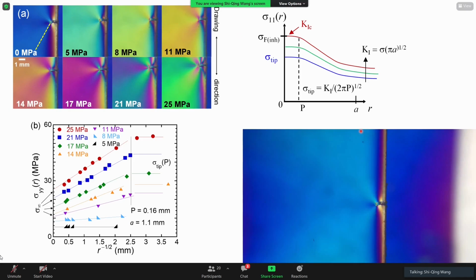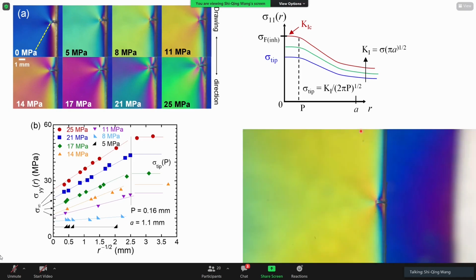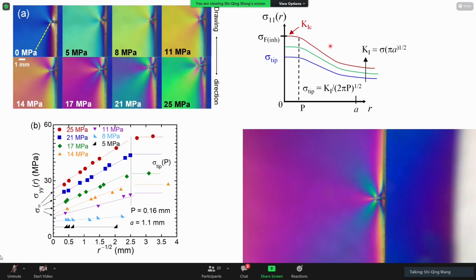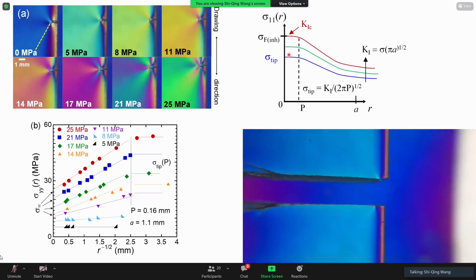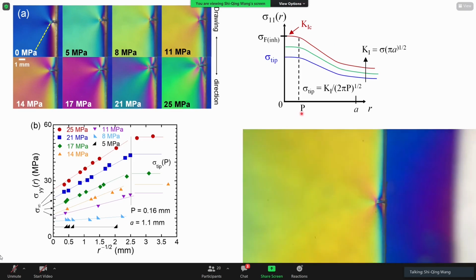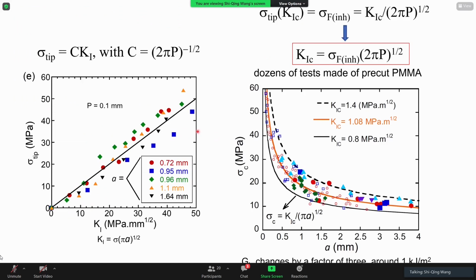This plot looks somewhat unfamiliar to fracture mechanics because I showed previously, I know I did it pretty fast, that the tip stress was supposed to converge to a common value. But we show that at the lower stress, the tip stress is lower. You can carefully take a look at the movie and be able to show that. Having learned that, my student Chaitanya used different styles of cutting the PMMA and reported his tip stress in that stress-saturated zone as a function of the operational definition of K. He found that this tip stress correlates with K linearly.